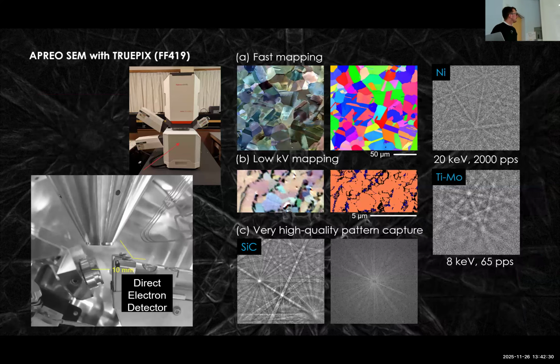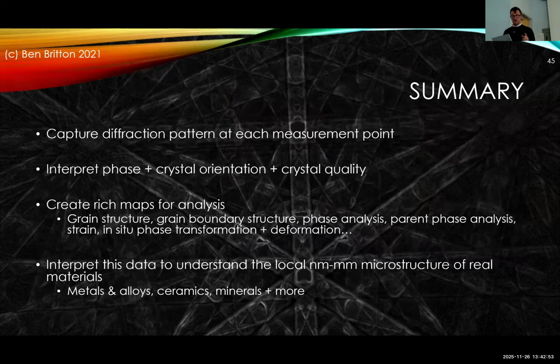And then the Apreo. We've seen this now live, but this is what it physically looks like. That's the system with EBSD in. So we can do fast mapping, as I've shown you. We can do low kV. This is 8 kV in a dual phase titanium molybdenum at 65 patterns a second for that example. And then for certain problems, we want beautiful diffraction patterns. And so that's a silicon carbide. It's one of the sharpest patterns you can get in the world on those sort of systems.